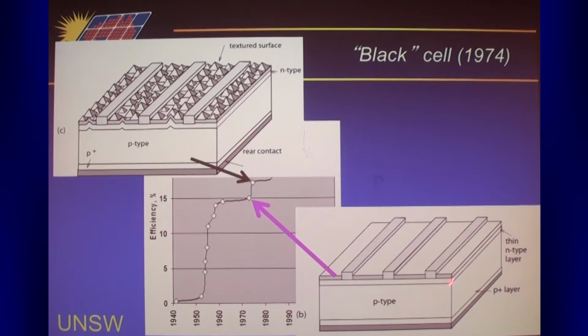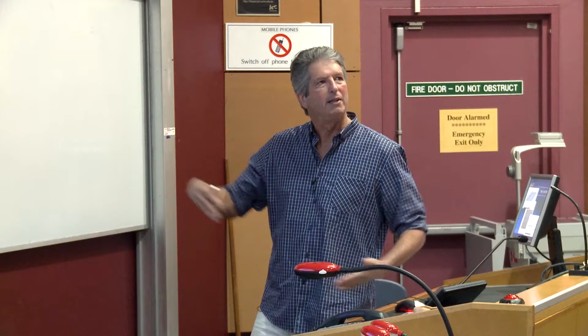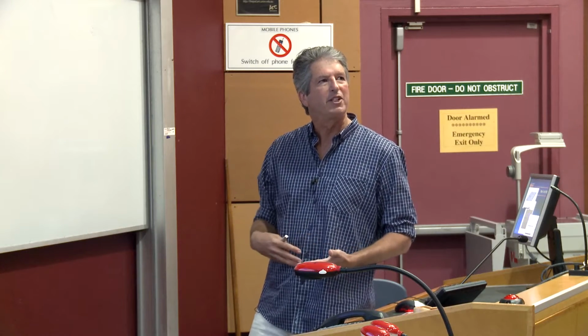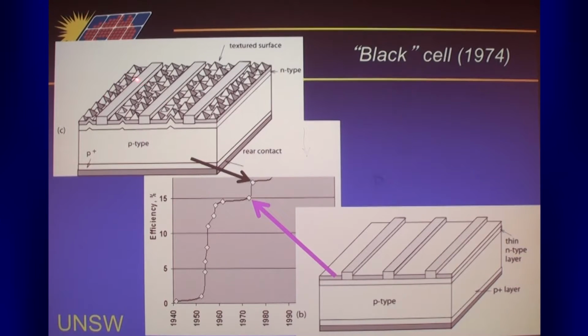But the major advance over this one was the use of this texturing of the surface to reduce reflection. So I think the reflection reduction technique is quite obvious. Light coming down will first strike one of the sides of these pyramids, and most of it will be refracted into the silicon material. But what isn't refracted in is reflected, but the angles are such that it has to get reflected downwards. So that means it has at least 2 chances of getting coupled into the silicon.